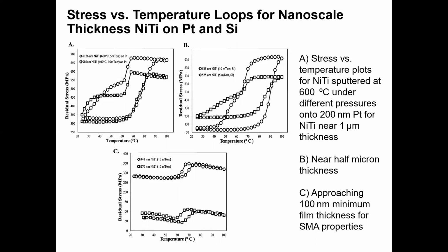And these stress curves are characteristic of the R phase transformation, where recovery stress is small and hysteresis is narrow. This is all consistent with other data where films below 400 nanometers thickness have a tendency to exhibit the same transformation response as seen here. But these nonlinear changes in stress are later used to drive actuation in a MEMS bilayer device.